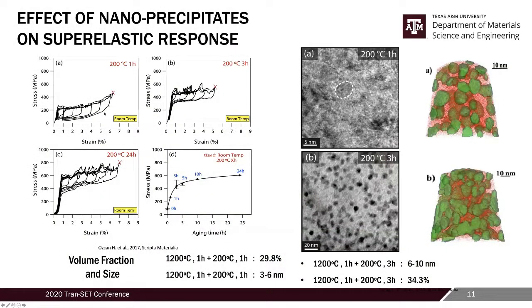But to get insight on the material properties, we looked at the effect of nanoprecipitates on the superelastic response. This graph shows that you can manipulate the superelastic stress levels, so the stress at which your material transforms, by changing the aging heat treatment. If you change from 1 hour to 24 hours, you can control these stress levels.